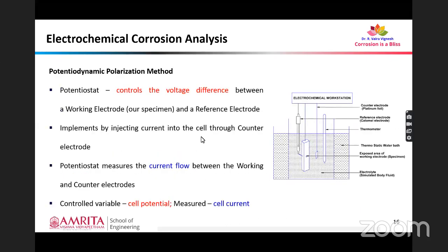And coming towards the potentiostat, as we have discussed already, the potentiostat is an equipment that controls the voltage difference between a working electrode, that is our specimen, and the reference electrode. This is carried out by injecting current into the cell through the counter electrode. Then the potentiostat measures the current flow between the working electrode and the counter electrode. From this, we can obtain the corrosion current of the material. So we can say that the controlled variable is the cell potential and the measured quantity is the cell current. Based on the value of cell current, we can interpolate the corrosion rate of the specimens.